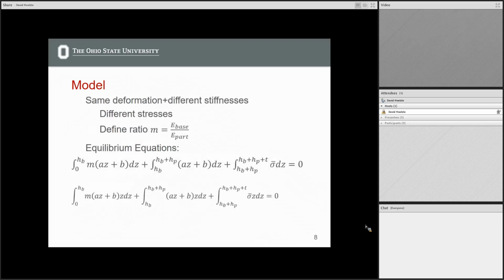So taking a look at what happens in between that interface, we're going to have the same deformation of the base plate and the part itself at that interface. However, those two materials have different stiffnesses. Therefore, they're going to develop different stresses. So we can define a ratio M here, which compares the stiffness of the base plate and the part itself. And doing so, applying Hooke's equation and the strain equation that we just showed, we end up getting our force and our moment equations to look in this form, where we have an integral across the base plate, an integral across the part, and then an integral across that top layer.